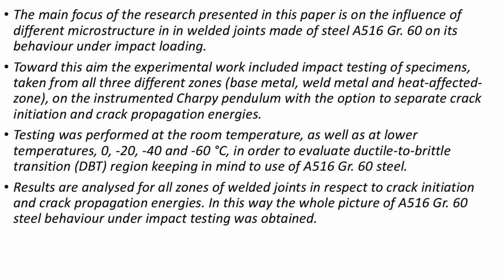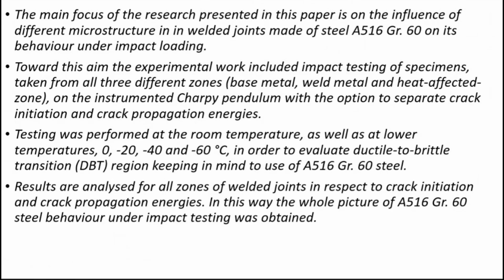So this is what is also written here. We have used the instrumented Charpy toughness pendulum, which can separate crack initiation and crack propagation energy, which is a very important issue. As it turned out, in this case, not so important. For what we aimed to do, it was almost irrelevant, because we actually tested these welded joints starting from room temperature down to 0, -20, -40, and -60. And the idea is to evaluate the ductile to brittle transformation temperature.